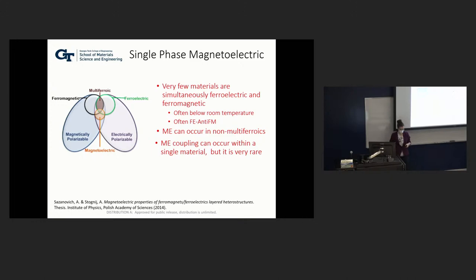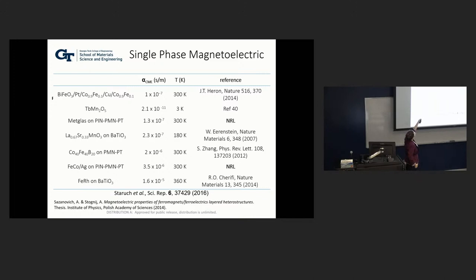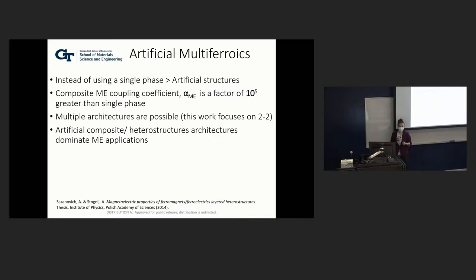And the other thing that I'll say is, in addition to being rare at room temperature, the coupling is actually pretty weak. So if you look at the terbium manganate, the response is significantly lower than the coupling that we see in other types of composite materials, right? So that leads me to my next point, which is this idea of artificial multiferroics. So as a community, because there are not a lot of materials that fulfill this type of coupling need, they've collectively moved to artificial structures. In this case, usually the ferro or the magnetic and the electrical response are decoupled. One material takes care of one portion and the other takes care of another, and they interact across an interface, right?